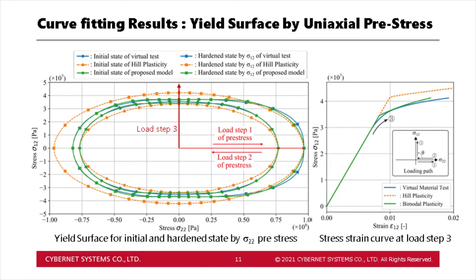The hardening behavior under transverse pre-stress was also verified in the same way. In this case, the yield surface is distorted more than the hardening due to shear pre-stress. Therefore, Hill's model clearly fails to capture the characteristics of material behavior observed by virtual test. Whereas, the proposed model successfully expressed the feature of large overhang in the pre-stress direction. Not only that, the yield behavior on the compression side is also accurately fitted.